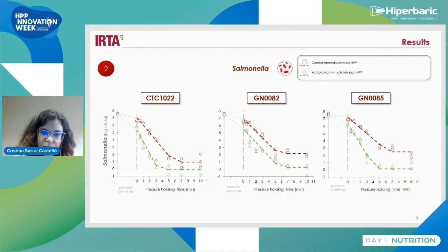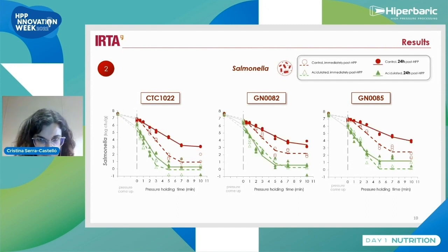If we don't only focus on the inactivation of Salmonella when we enumerate it immediately post high pressure processing, we can also observe differences with the counts made 24 hours post high pressure processing. All the inactivation curves move upwards, especially those from control product. We can see that these 24 hours result in a lower inactivation of Salmonella.